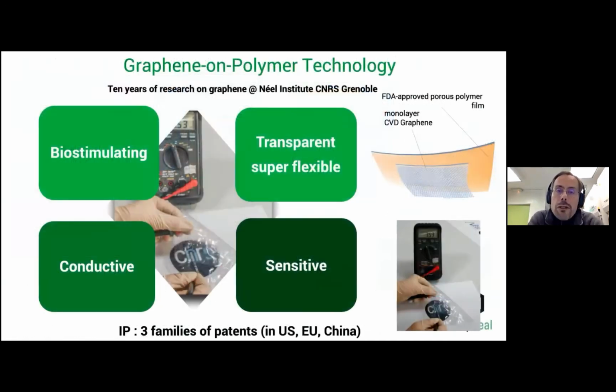So why is graphene on polymer an ideal material for making bandages? First, we've seen it's biostimulating. It's a conducting material, so you can use it as an electrode to apply voltages, and that's quite important because there is a large field of research and even products on the market where you electrostimulate the wound by application of pulses of voltage. It's also transparent, so you can see through, which is quite important for a bandage. Extremely flexible, because we can make films of 5 micrometers, which are very conformal and can go into deep wounds. And it's sensitive, in the sense that you can measure the resistivity side to side of the bandage, and this will give you an idea of the composition of the liquid in contact with the wound.